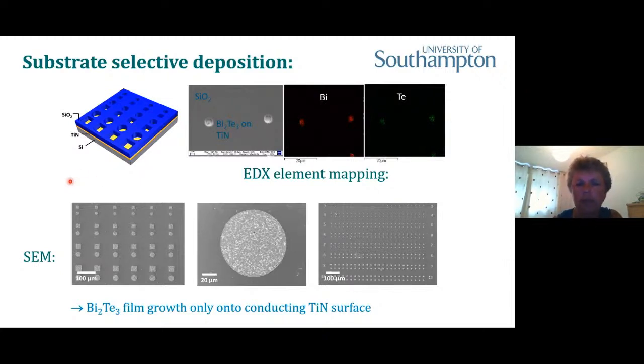And what we've been able to show is that by using this single molecular precursor, rather than combining lots of different things in a CVD reactor, we get a really high level of discrimination between silica and titanium nitride. And I'm illustrating that. I hope you can see the colors okay, but the SEM image here shows the deposition into two of these adjacent recesses, and you can see the material at the bottom here. And then we can do the EDX mapping to look at the composition, and it's very clear that the bismuth and tellurium are only occupying the regions where the film has grown on top of the titanium nitride.